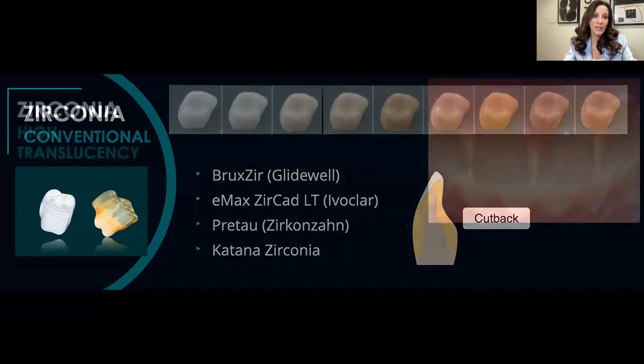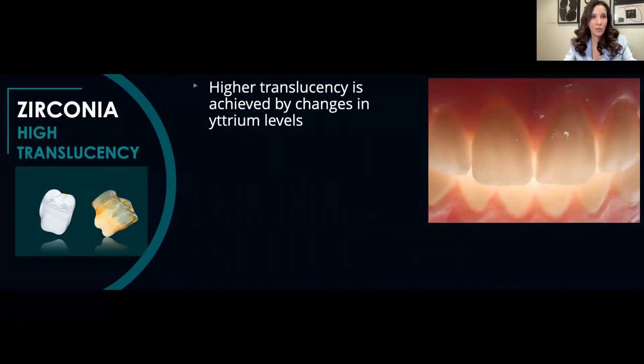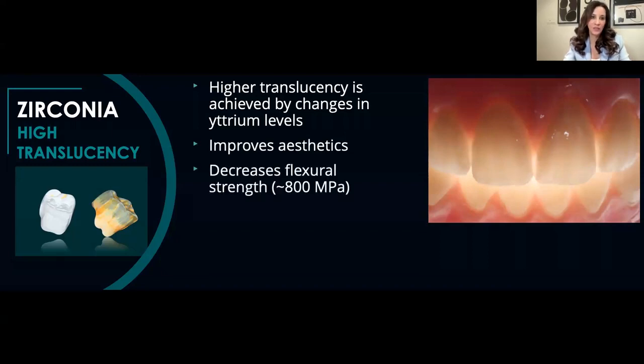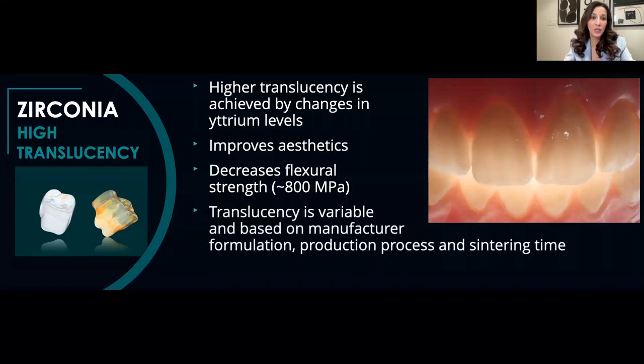Now, we also have the ability to have a more aesthetic material, a more high translucency zirconia. And higher translucency is achieved by changes in the yttrium level in the material. By altering the yttrium levels, you can get improvement in aesthetics. But the flip side of that is that you do, in fact, have a decrease in flexural strength. So the high translucency, or the aesthetic zirconias, are weaker than conventional, but yet stronger than your particle-filled glass. The strength in that category of material is somewhere around 800 megapascals. Now, the translucency is quite variable based on your manufacturer, formulation, and production process, as well as sintering time. So understand the material that you're using.